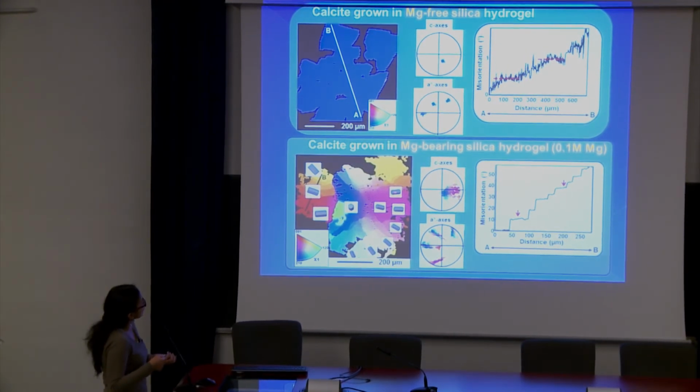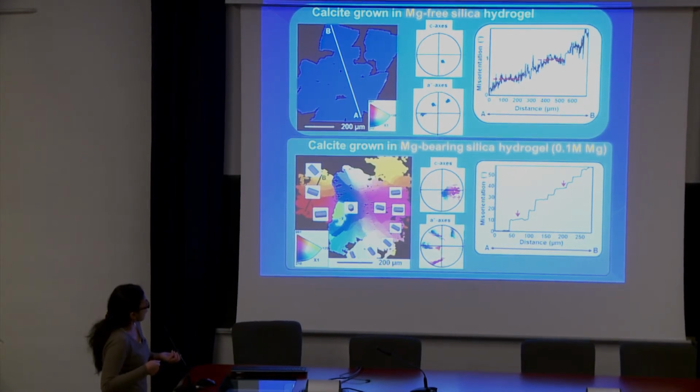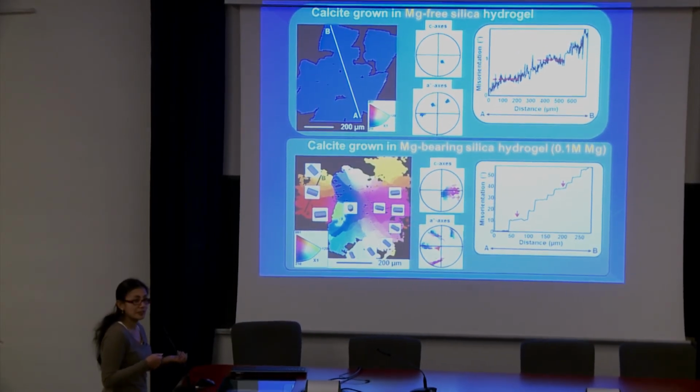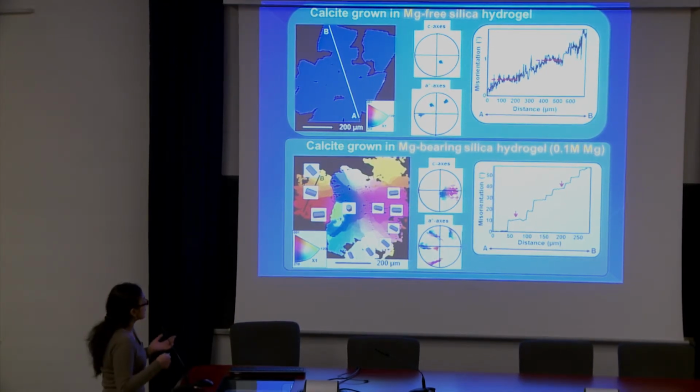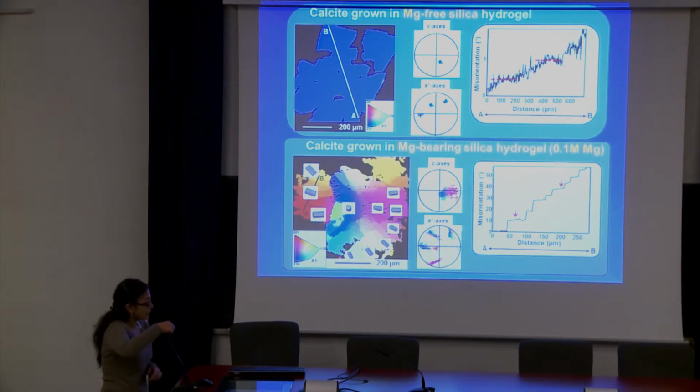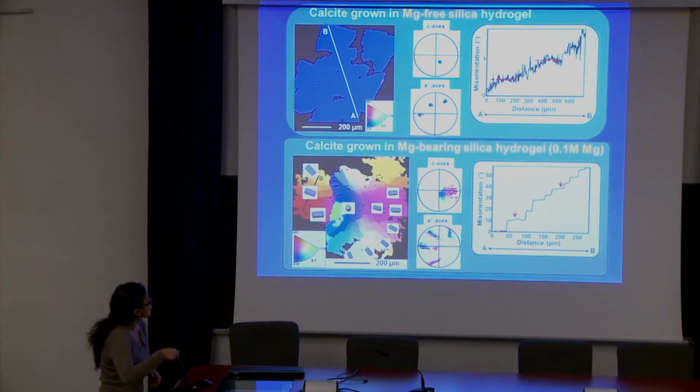So this is the crystallographic 3D here. And I would say it's half spherulite, or partially spherulites. Why is it so? Because if you pay attention here in the middle, in the core of this aggregate, it has the C-axis pointing toward us. And then it is spherulites because the C-axis here is going toward the middle. So I would say this is half spherulites.